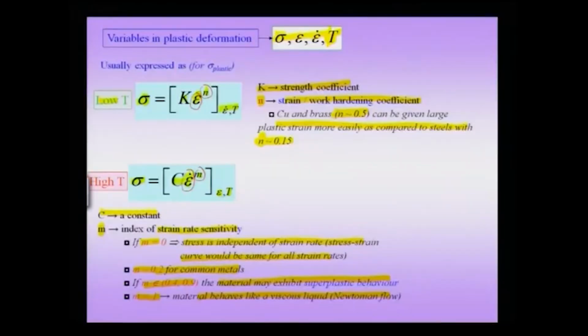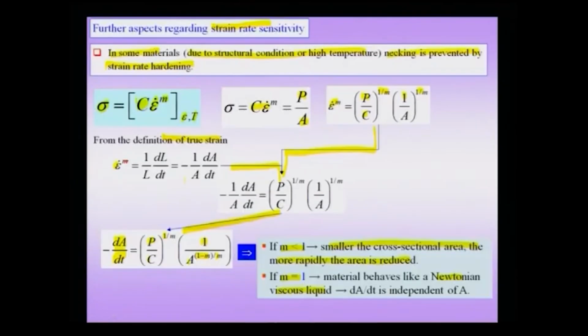Therefore, there are two empirical formulae commonly used in the literature, which give you the connection between these variables: sigma is equal to k epsilon power n, where n is the work hardening or strain hardening exponent. At high temperature, you can write sigma equal to c epsilon dot power m, where m is the strain rate sensitivity. And if I want to study the effect of strain rate sensitivity, I can talk in terms of reduction in cross sectional area per unit time.